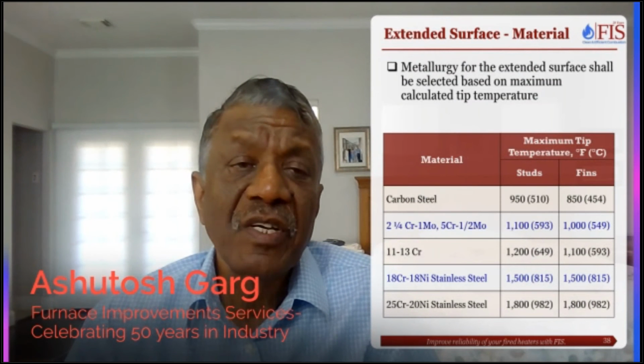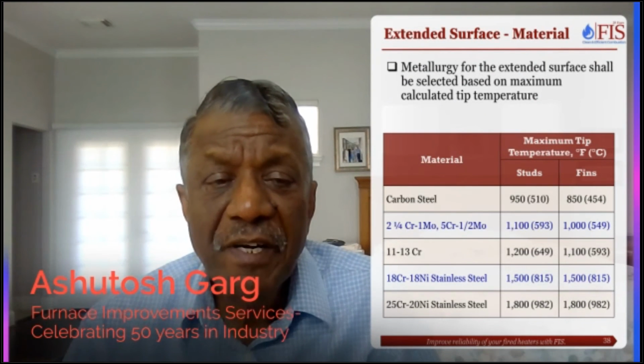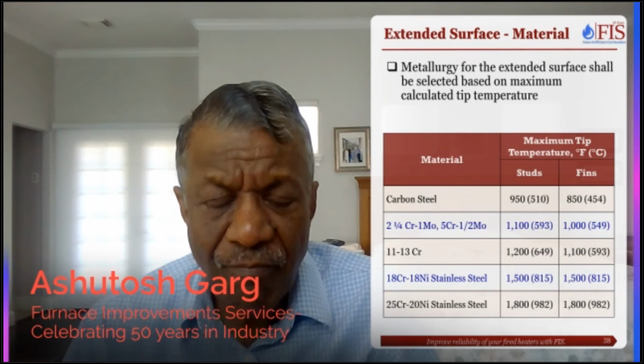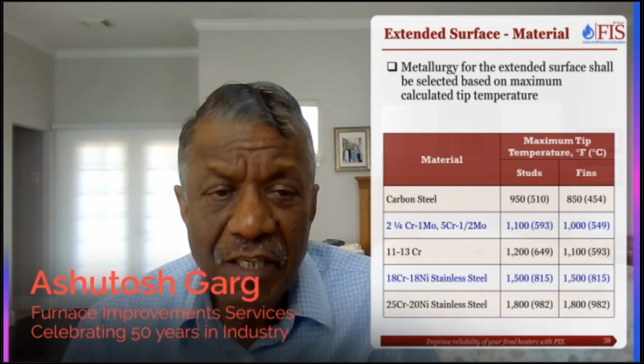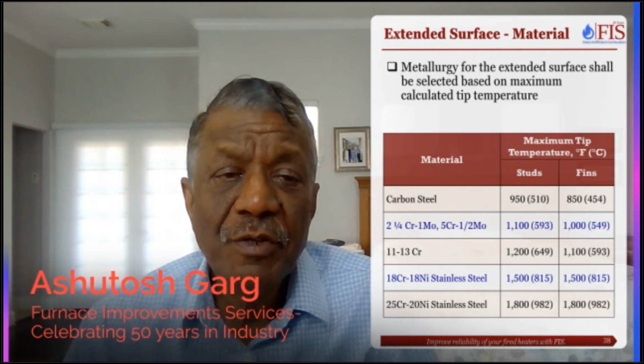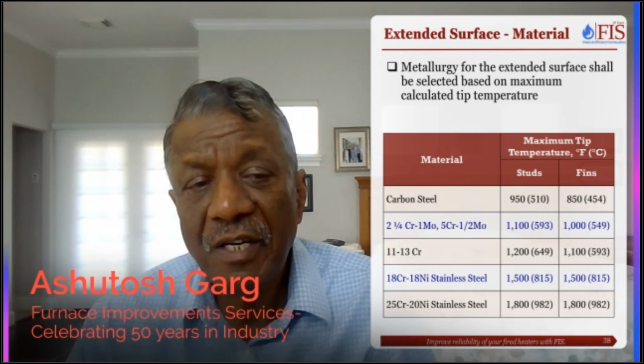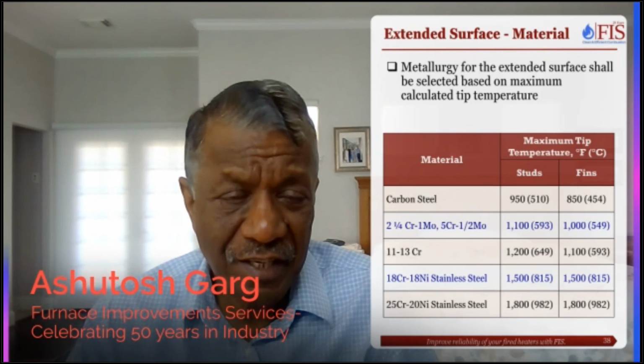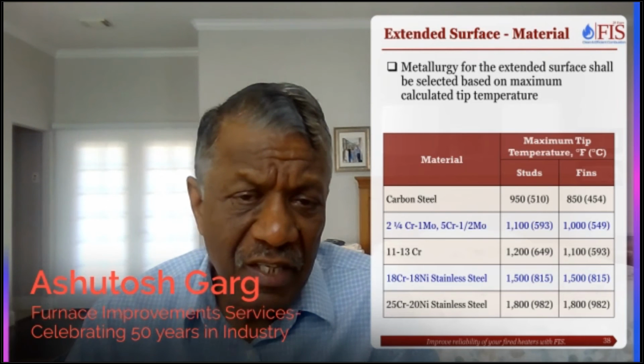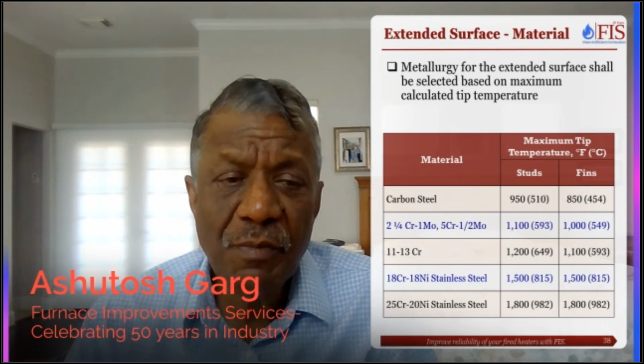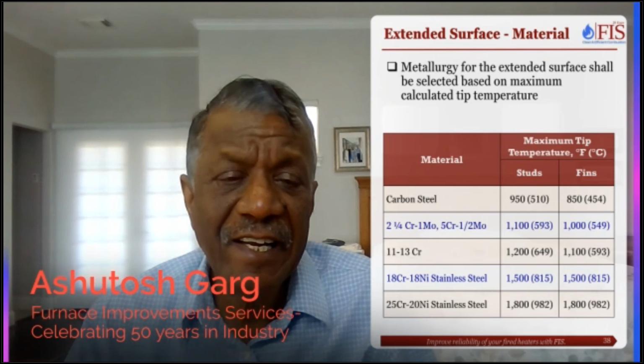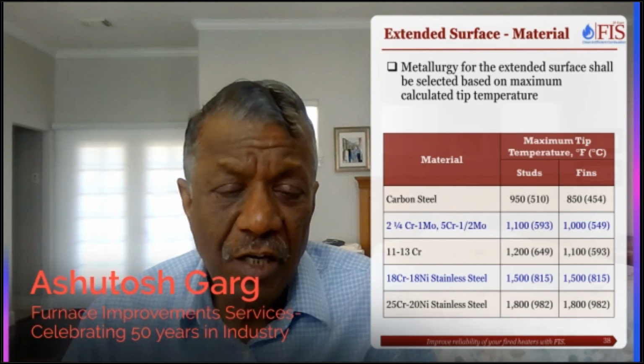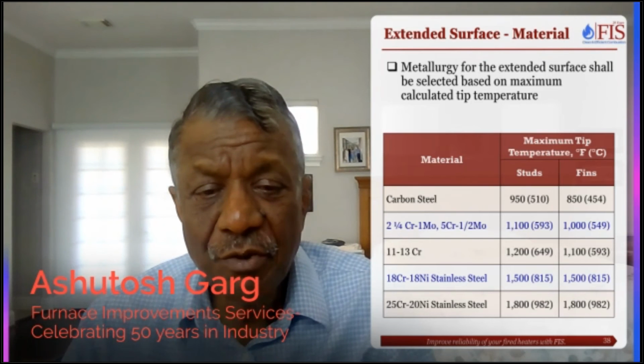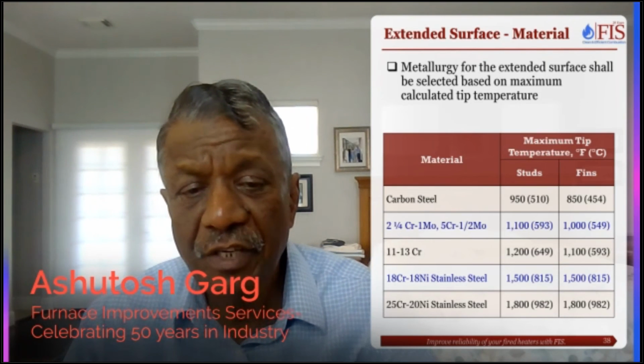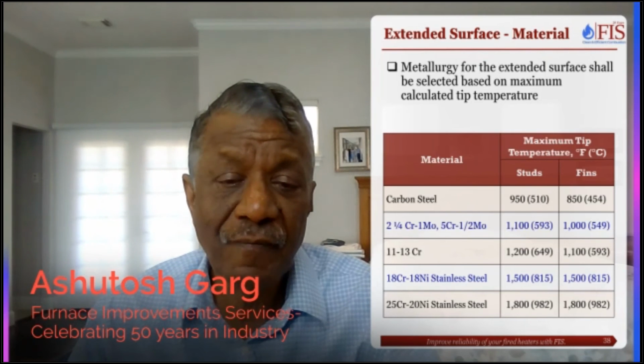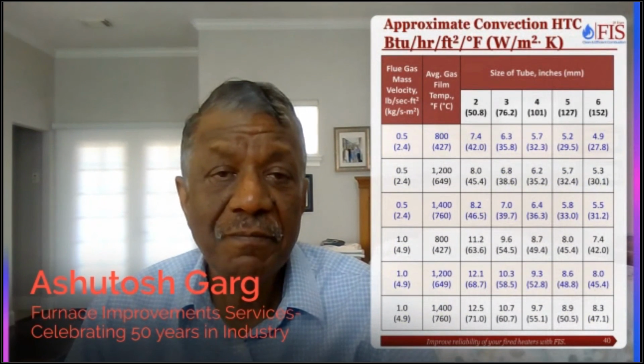When we talk about fin tube metallurgy, carbon steel is most common and it can be used up to a maximum fin tip temperature of 850 degrees F for fins and 950 degrees F for studs. Then we have alloy steel, 2 1/4 chrome is also very common material, and 18-8. 25-20 or SS310 has been used very, very rarely. In fact, it may be better to use bare tubes when we come to these fins.